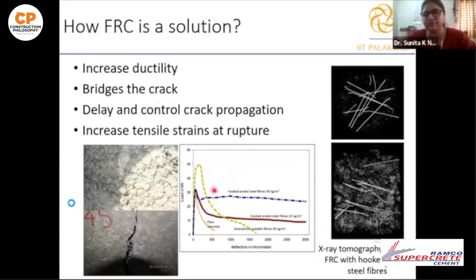All because of this post-cracking characteristic, which is demonstrated in the load deflection curve here. This blue one is for a plain concrete with almost very brittle failure. Sorry, the orange one is the plain concrete, whereas all the other three show some post-cracking capacity. That means it is resistive enough to hold the crack together.